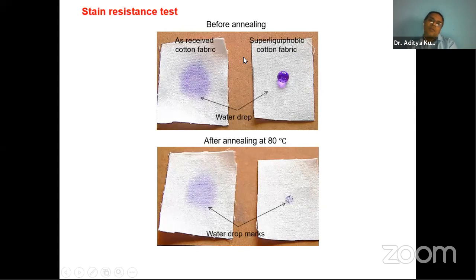Here, what we have done, we created super hydrophobicity on cotton cloth, right? And we put colored water on the uncoated one and the coated one. After drying, what we have seen, it definitely becomes dry, but after drying, the uncoated one left so much stain. But on this super hydrophobic surface, after drying, it leaves no stain marks. So because of the super hydrophobicity, we can say we can have stain resistance.